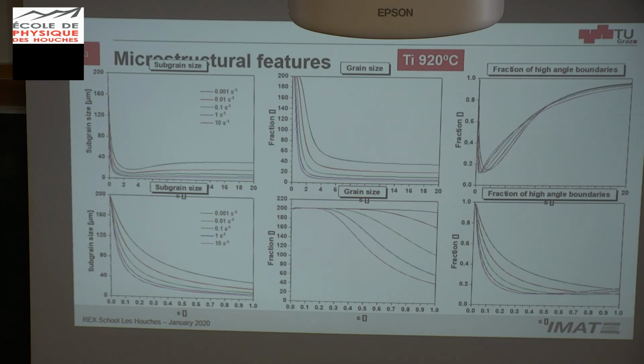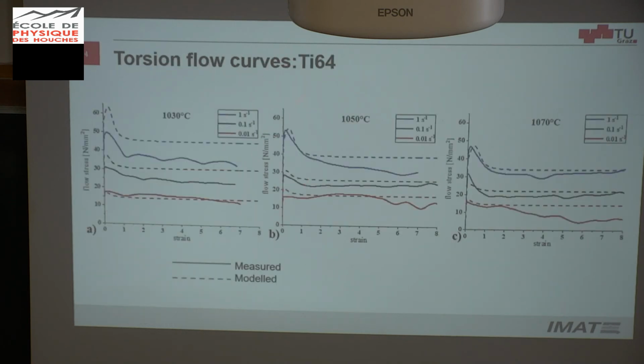The most interesting part is that we can catch the subgrain size: first a drop and then an increase, very similar to the measurements that we have done of the crystallite size in the in-situ measurements. We can get the grain size as well, so the refinement of the grains. You can think about extrusion processes. We get the fraction of high-angle grain boundaries, which, if we start with a recrystallized material, first decreases and then increases until we reach recrystallization. These are just zooms up to only one of deformation. The same for torsion flow curves. Here we still have some issues to clarify.